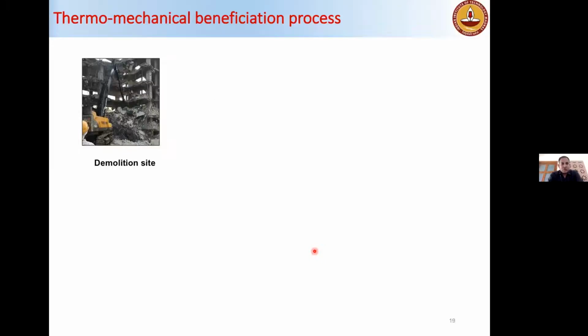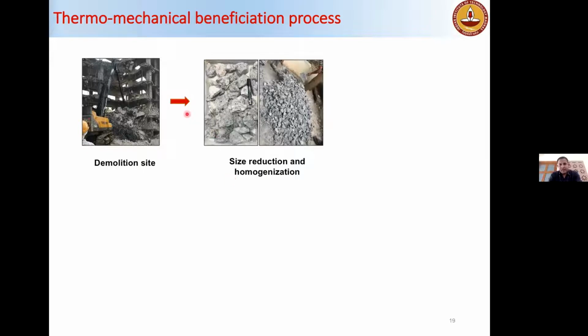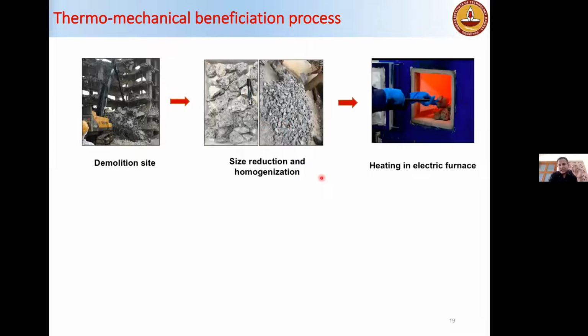In Chennai, there was this demolition site. We got the waste from it, and the rebars were already removed. Then we did the size reduction. We optimized this process also. We used different sizes of concrete pieces, and then we used an electric furnace to heat this. Various temperatures were tried, starting from 350 degrees C to 500 degrees C.